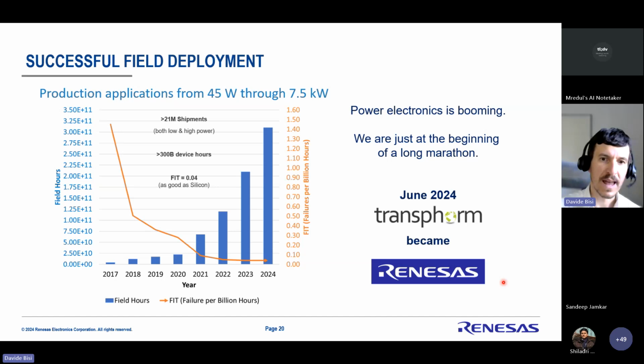So thanks to the reliability and the quality of these devices, we witnessed market adoption. So you can see here across the years, we see how GaN, our Transphorm GaN, is penetrating the market. So with significant field hours, 21 million parts already in the market in applications that go from 45 watts to 7.5 kilowatts. With exceptional performance and a failure rate which is as good as silicon. So this is a great start, but as we know, this is only the beginning.